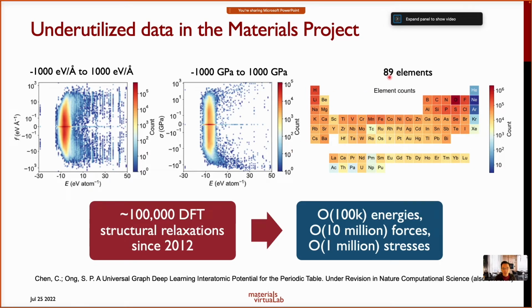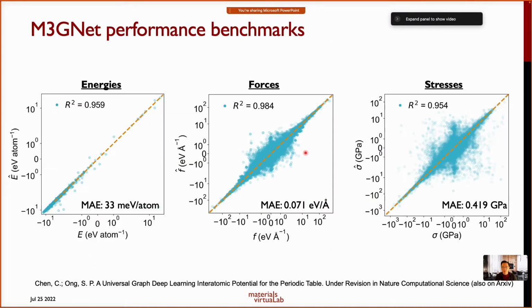And this entire data set covers 89 elements of the periodic table, right? What we can do now is that instead of building a potential for some limited chemistry, we can take this very, very big data set and throw it into the M3GNet architecture and build what we call a universal interatomic potential for the entire periodic table. Okay, so that's what we did, and we can show that we can build an interatomic potential that can predict the energies to within about 33 meV per atom. Not as low as if we just build it on one element, but remember this is for 89 elements of the periodic table, so this is actually very good for that purpose. We can predict forces to within 0.07 eV per angstrom. Again, very good, right? This is good enough for us to do structural relaxations with it, and stresses are a bit more mixed, but we can get them to within about 0.419 GPa, right?